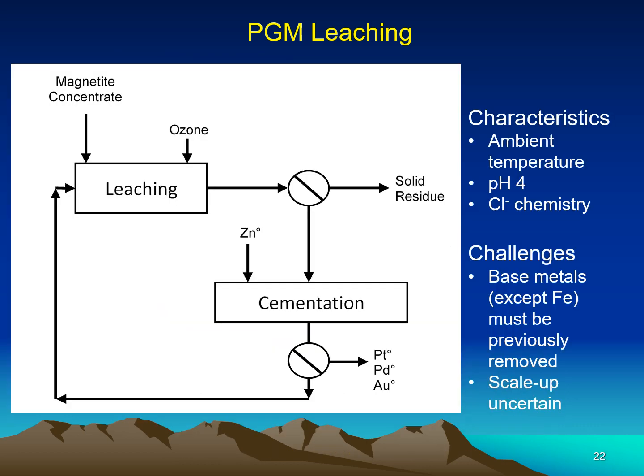So the process that we have devised for this is for these magnetite concentrates are leached with ozone at pH 4 with a high concentration of chloride ion in the form of sodium chloride, and then the solid residue is filtered out, and the pregnant solution is then cemented with zinc powder. Out of this we get platinum metal, palladium metal, and also gold is also leached and cemented in this case, and we can recycle the salt solution back to the leaching.